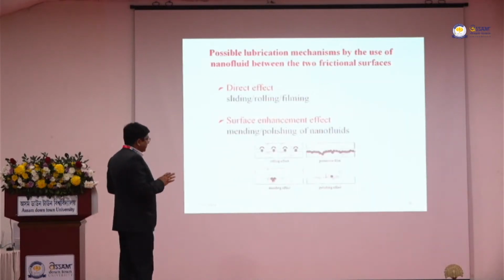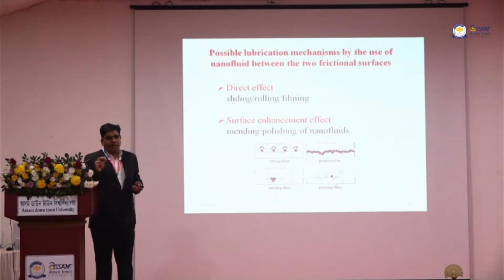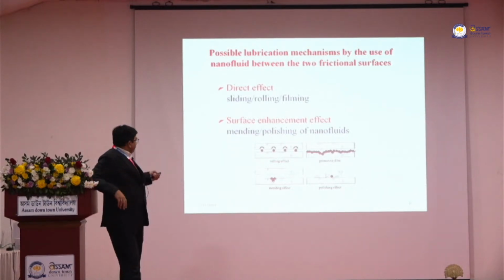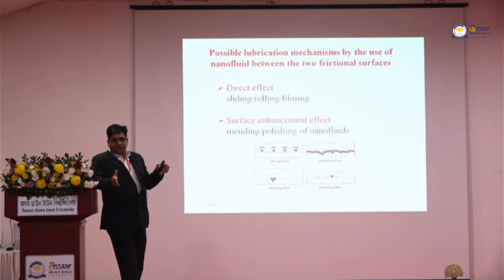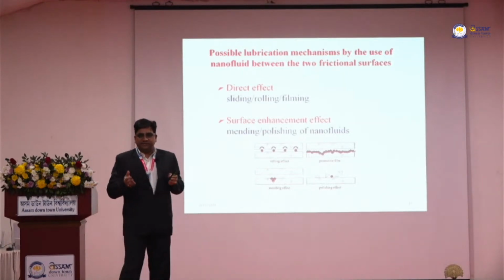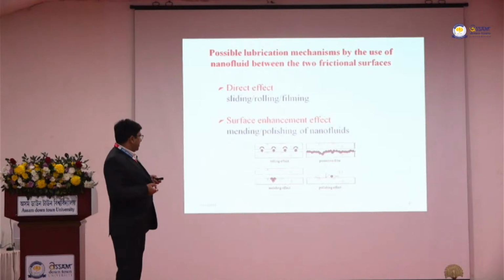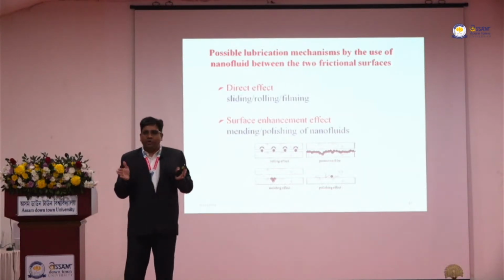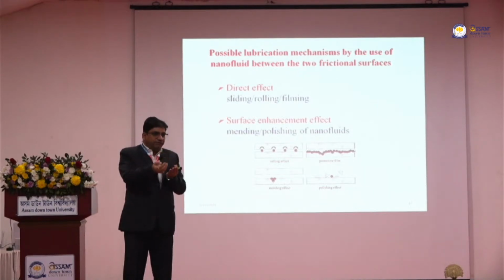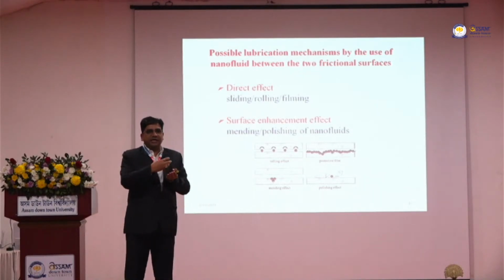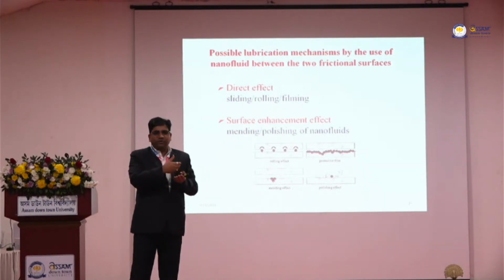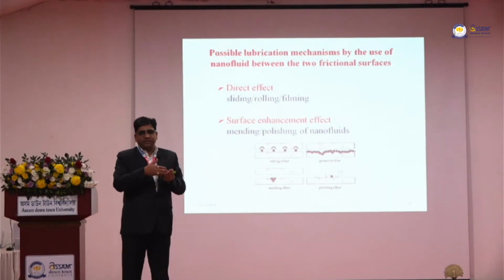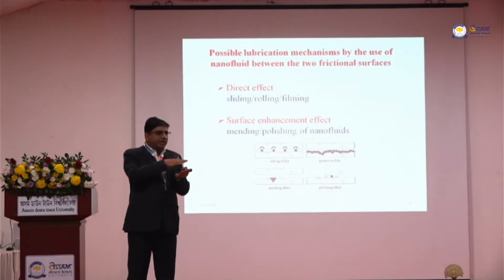So what are the benefits of adding nanoparticles into the cutting fluid? Basically, if we add some particles inside any liquid, depending upon their shape, most of the particles are spherical or similar to spherical in shape. So what they do is the direct effect and surface enhancement effect. If we have two bodies sliding over each other, and we put a third body, like spherical particles, it will create a rolling effect. So it will reduce the friction.